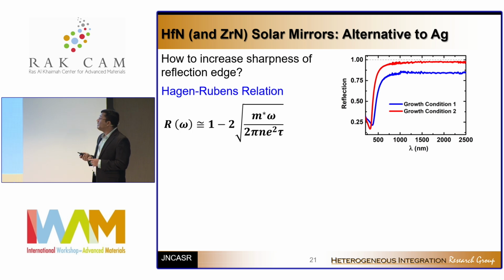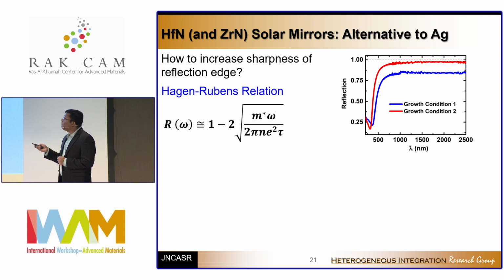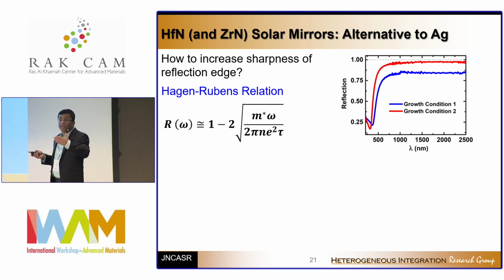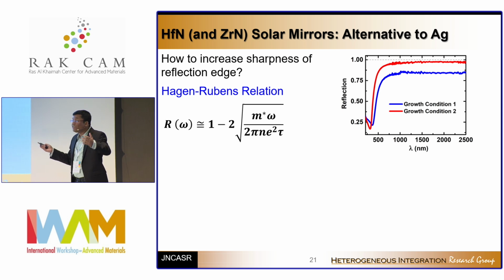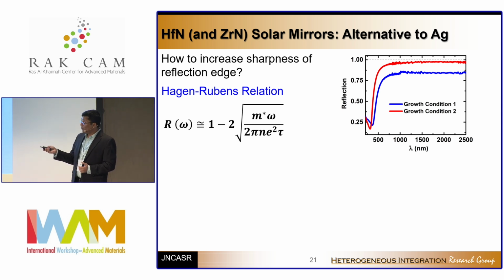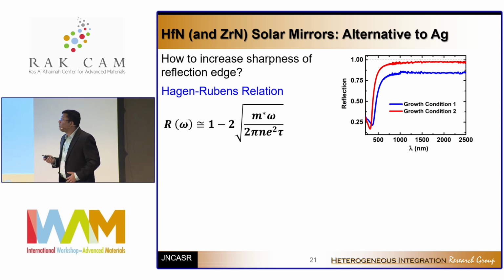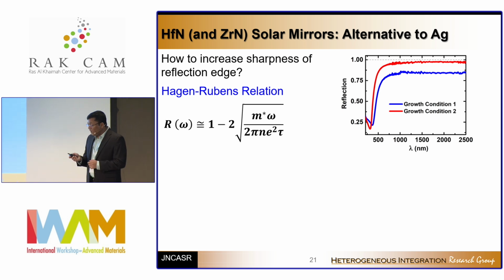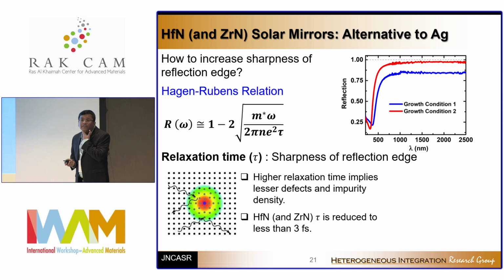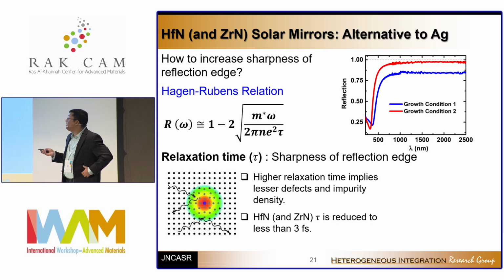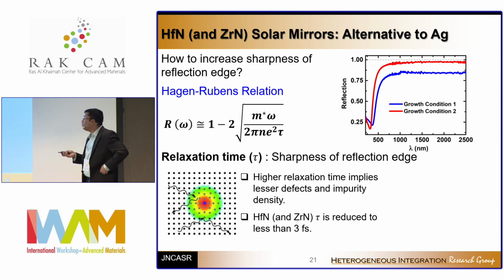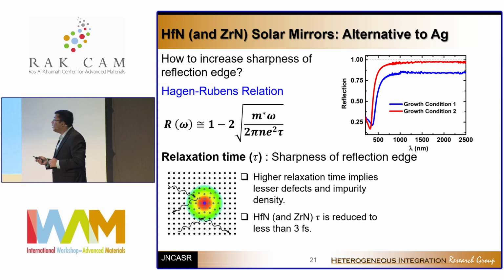And our students did look at the problem from fundamental perspectives, and we eventually realized that you really have to have a very high tau, which is the relaxation time. Basically, in the ideal case, if you don't have any scattering, tau will be infinity, 1 by infinity will be 0, R will be basically 1. So not only do you need a perfectly matched plasma frequency, you also need 1 by tau to be very, very small. And you can achieve that if you make single crystal epitaxial films where there are not many defects, and because there are not many defects and not much scattering, you basically can achieve such sharp reflection edges.